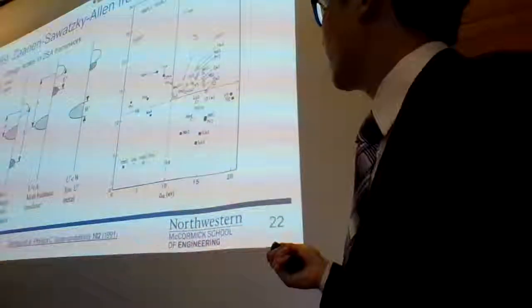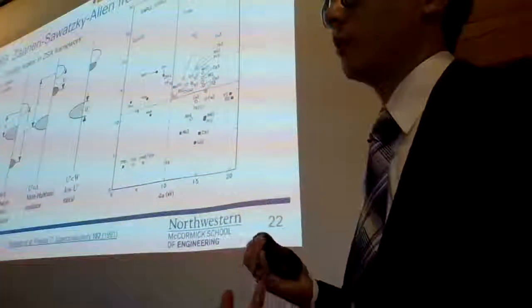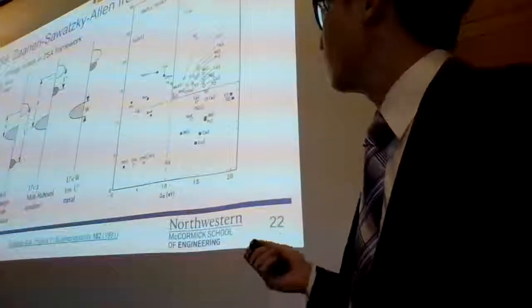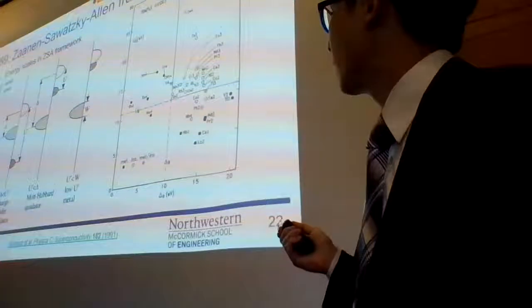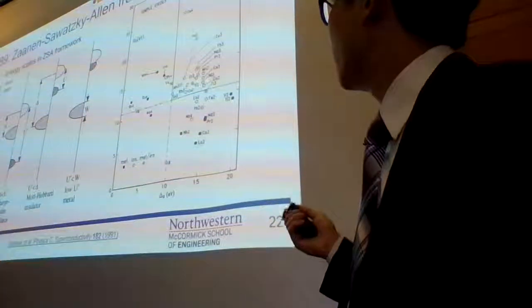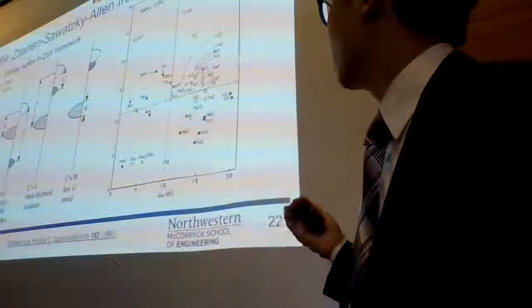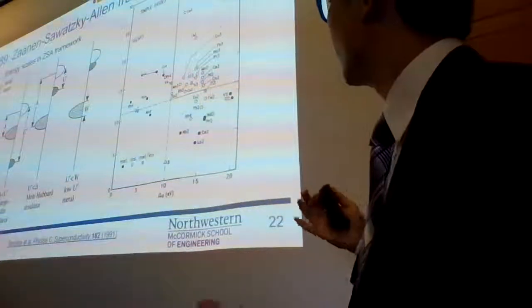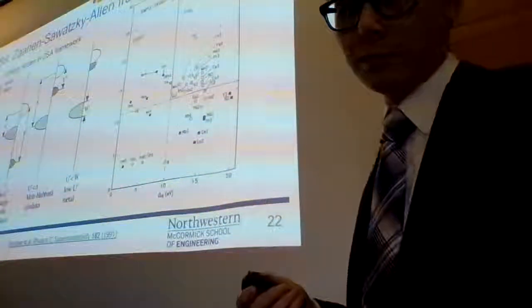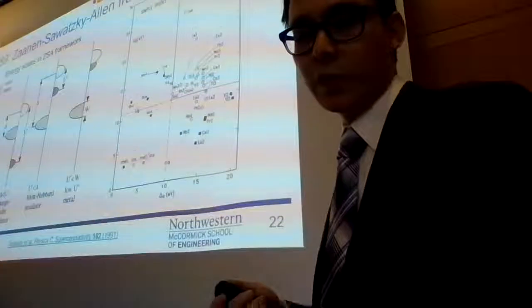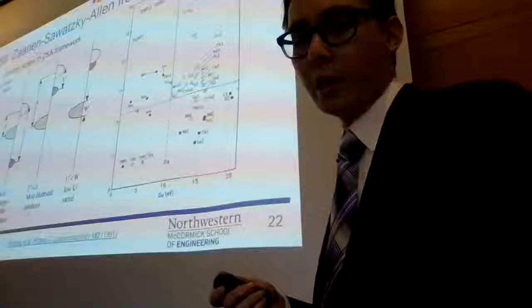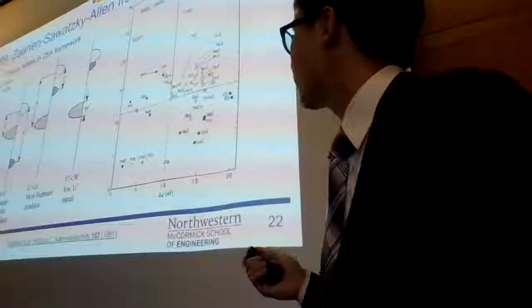And they drew these lines by hand rather than using any sort of rigorous statistical learning technique, but it worked quite well. And they reasoned that things that were close to this line, like titanium oxide, were known to have metal insulator transitions. But they were sort of limited by the amount of data that they had and their choice of descriptors.